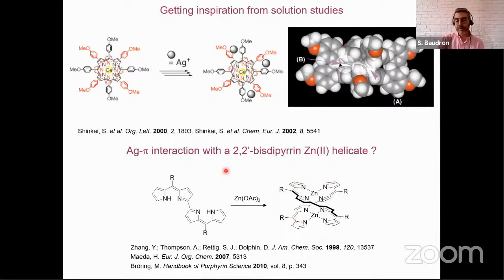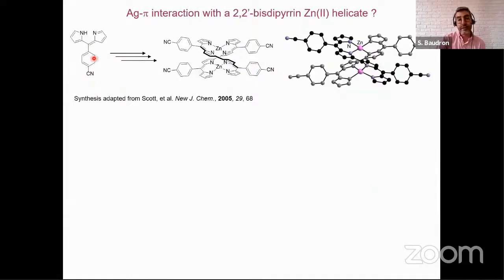And what was of interest to us is that if you look at this type of helicates, they actually have 4 pairs of pyrrolic systems that are facing each other, but are arranged in an analogous fashion to what is observed in the double-decker cerium porphyrin system. Also, this type of compound had not been studied in the literature for the assembly with silver 1 cation, so we thought that maybe there was an opportunity to do so and to complement our study. Another interest in those ligands is that their synthesis starts from the monodipyrrin ligands. So in a multi-step way, we went from our original ligands and we prepared this binuclear zinc helicate, characterized it and also crystallized it.